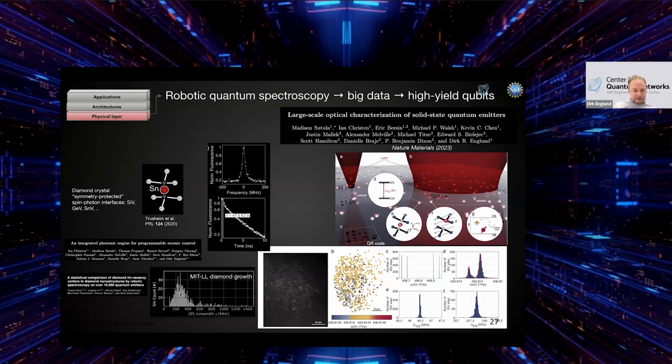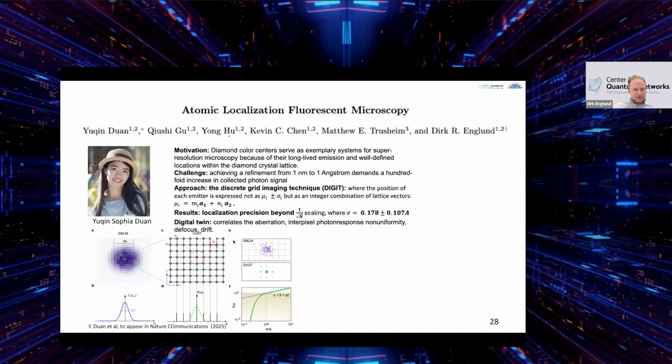Okay, but still not good enough. You see, this is one example of the many outstanding problems with color centers or any kinds of solid state emitters for quantum memory applications, is that there is some additional noise that immediately will affect your coherence, your gate fidelities of this distributed entanglement experiment. And there's different ways that people deal with that. One is by filtering. So you can filter and then you trade fidelity against success rate. Or you use variations of entanglement schemes, and we'll get back to that in a moment.